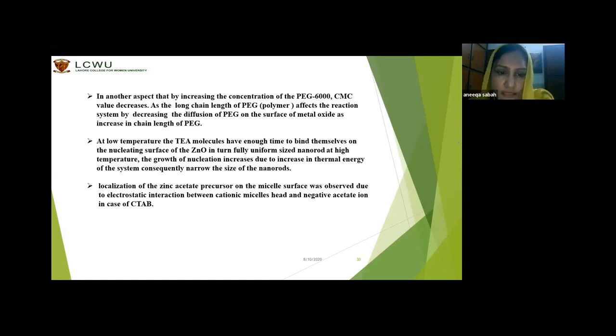Localization of zinc acetate precursor on the micelle surface was observed due to electrostatic interaction, because it has dual nature, positive and negative ions. There is electrostatic interaction between the cationic micelle head and the negative acetate ions.